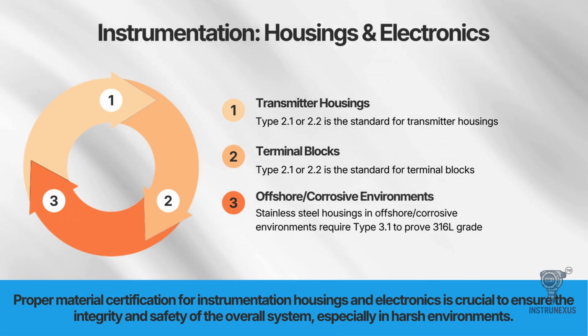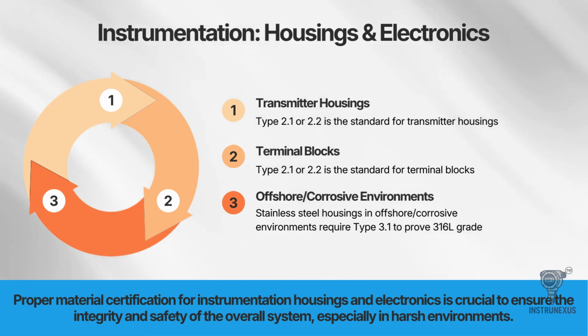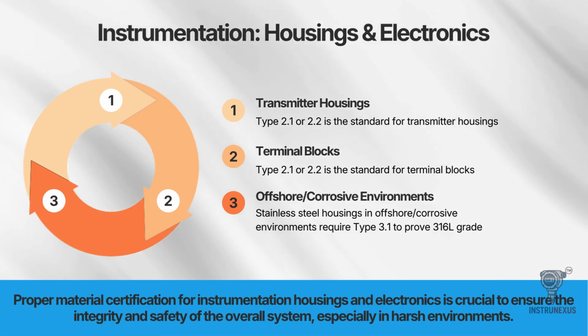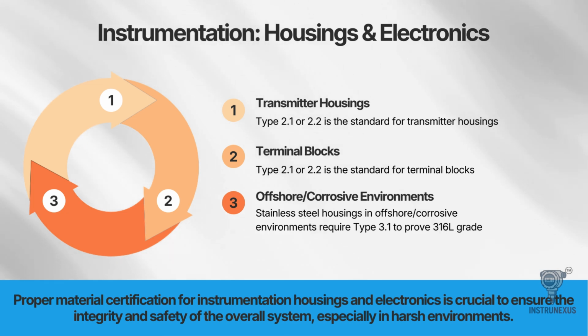However, if you are operating in offshore or corrosive environments, the specification must change. In these cases, stainless steel housings require a Type 3.1 certificate to prove they are genuinely 316 grade. Using a lower grade here could lead to corrosion and loss of the instrument. Proper certification here ensures the integrity of the system, even in harsh environments.